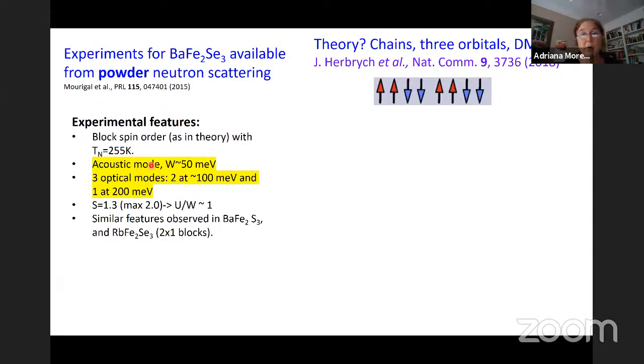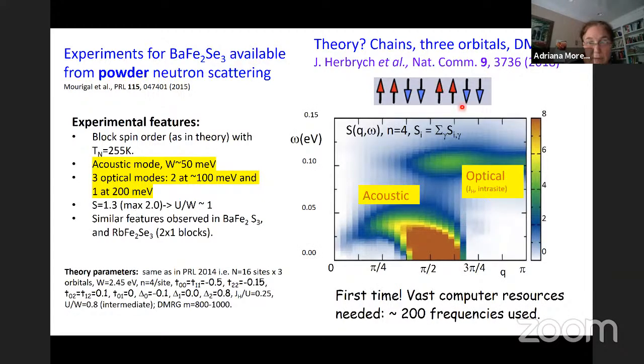We worked with the 3-orbital model using DMRG in chains, using the parameters that gave us these size-2 blocks, and we calculated S(Q,omega). This is what we obtained: an acoustic mode with a bandwidth of 50 meV, and an optical mode at about 100 meV, in very nice agreement with what the experimentalists found.